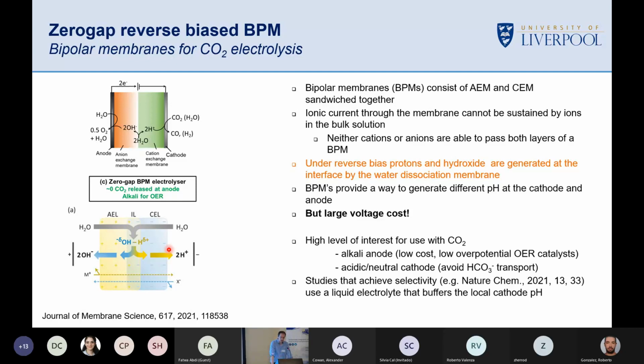When they've been used in this reverse bias mode for CO2 reduction, they've generally given just very, very low Faraday efficiencies for CO2, under sort of 10%. The standout examples come from Tom Mallouk's group a year or two ago now. But here what they did was bring the pH back up of the cation exchange layer. So they made it into a weaker acid surface at the top by modifying the polymer structure and building up in a layer by layer way, which means you get the selectivity, but of course you're still going to have the carbonate problems. They brought it back up to pH 7, 8.